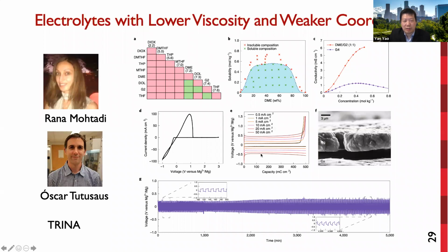In asymmetric magnesium copper cells, even at 50 milliamp per centimeter square, we still can reach a Coulombic efficiency of about 99.7%. The morphology of magnesium plated on copper shows dense, smooth, and dendrite-free morphology. This is deposited at 20 milliamp per centimeter square for an area capacity of 3 milliamp hour per centimeter square. We can also apply similar conditions for symmetric cells over 5,000 minutes. The smooth voltage profile indicates effective mass transport in the electrolyte. So these results consolidate magnesium metal as a safe anode even under demanding conditions.